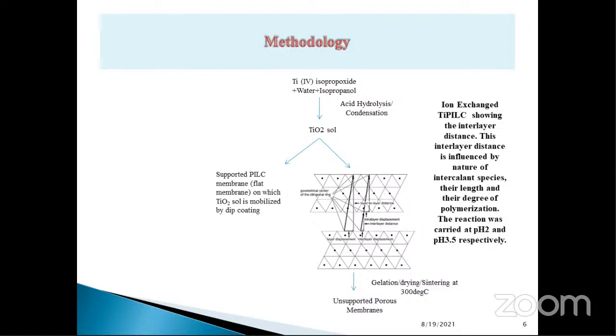The supported membrane material was made by dipping the flat disc support into the titania sol, and then it was dried and sintered at various temperatures from 300 to 600 degrees centigrade. Whereas the unsupported membrane material is made by draining the excess sol from the support material, and then that was dried and sintered at various temperatures from 300 to 600 degrees centigrade, and that provided the basis for the characterization purposes.